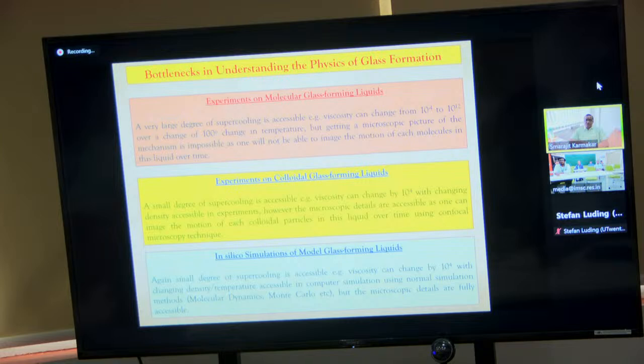But the difficulty comes when you try to access a very large window of relaxation time or viscosity. In colloidal experiments, the largest viscosity change that you can study is of the order of 10 to the 4 to 10 to the 5. In simulations, the biggest difficulty is also the time scale. If you push it a little bit more, the largest change in viscosity one can study can be 10 to the 5 to 6, which is very similar to what you can achieve in colloidal experiments.